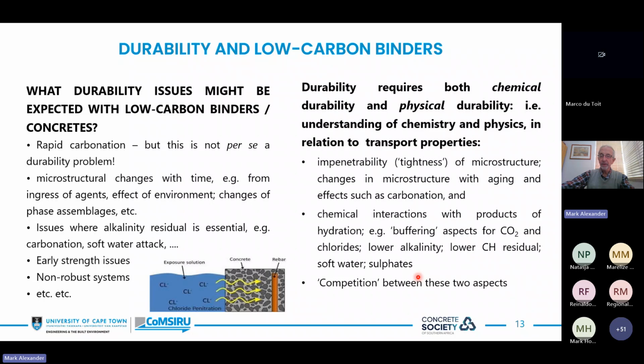And microstructure can change with aging and things like carbonation. And then on the chemical side, we need adequate hydration products, interactions with those products with various aggressive agents, the buffering aspects for carbon dioxide and chlorides, the alkalinity issues, the lower Portlandite or calcium hydroxide residuals, the soft water attack, and the sulfates, and so on. And then there's always a competition between these two aspects, which has to be understood.